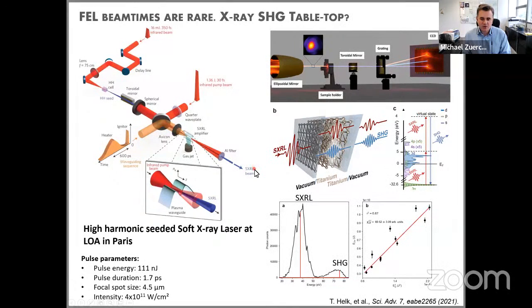Indeed, we can show that we observe it. These are the raw spectra. I will admit that the spectrometer was not very well aligned because of some geometric constraints. That's why these spectral lines are very much broadened out. In reality, these 2 features are very narrow band, a few tens of milli-eV. This doesn't really limit the interpretation, since we still have 2 separate humps that we can integrate and look at the statistics. That's what we really cared about: to see the second order response.